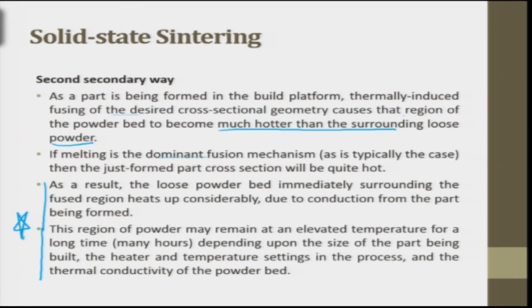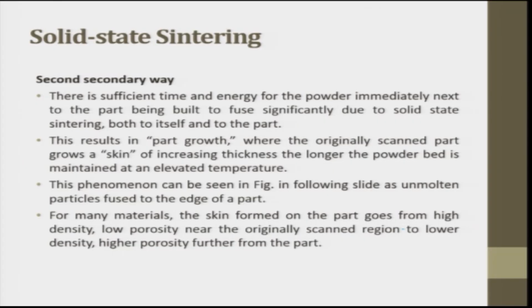This region of powder may remain at an elevated temperature for a long time depending upon the size of the part being built, the heater and the temperature setting in the process, and the thermal conductivity of the powder bed plays a very, very important role. There is sufficient time and energy for the powder immediately next to the part being built to fuse significantly due to solid state sintering, both to itself and to the part. So next to the part there will be sintering happening. This results in part growth, where the original scanned part grows a skin of increasing thickness the longer the powder bed is maintained at an elevated temperature.